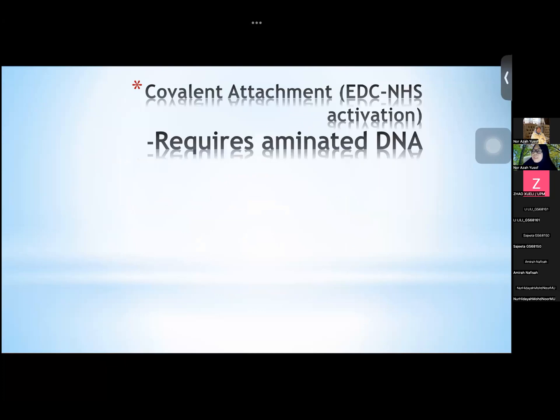Now is chemistry. Just now, I talked about carbon. Carbon is simple adsorption, meaning it's just adsorbed on the surface of the carbon. It's a physical adsorption; it doesn't have any chemistry. The same goes for polymer: it is due to the microporosity of the polymer. The bioreceptor is entrapped in a cage in the microporous structure. It does not involve chemistry. It's physical. But now, covalent attachment. There is simple chemistry involved.